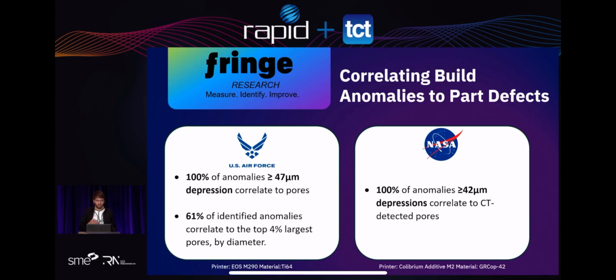And so our hypothesis that we're testing next is this 40 to 50 micron range, is that a function of layer thickness? Is that strong correlation and that threshold for when we should cancel a part based on layer thickness? Or how do we establish these thresholds for other materials and make this a repeatable process for any company that wants to predict porosity in the final part?